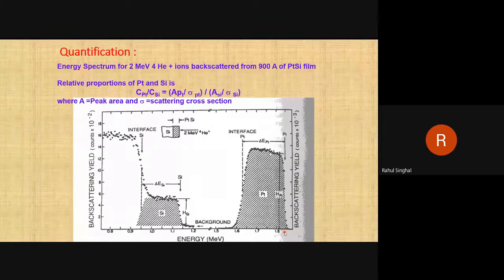Okay, so then your data will tell you that you have these two elements present in your material. Suppose you have deposited only platinum and silicon here, and suppose at low energy you are getting one more peak. From the kinematic factor I can find out that its energy corresponds to the energy of oxygen. It means we are getting a third peak of oxygen in our sample. That means our sample is not pure, it has some oxygen also, in the form of platinum oxide or silicon oxide.